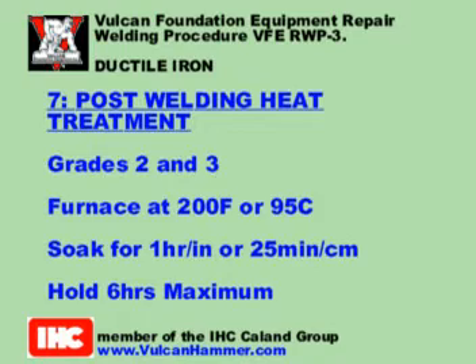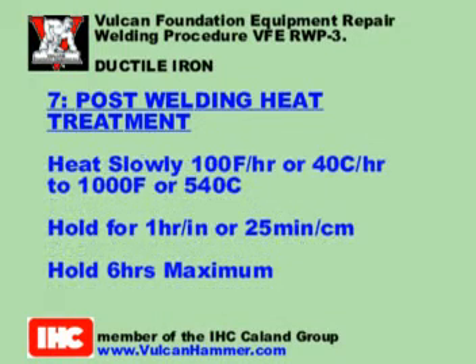Grades 2 and 3. Place in a furnace at 200 Fahrenheit or 95 Celsius and soak for 1 hour per inch or 25 minutes per centimeter, 6 hours maximum. Heat slowly at 100 Fahrenheit or 40 Celsius per hour to 1000 Fahrenheit or 540 Celsius and 200 Fahrenheit per hour or 95 Celsius per hour to 1650 Fahrenheit or 900 Celsius. Hold 1 hour per inch or 25 minutes per centimeter, 6 hours maximum.